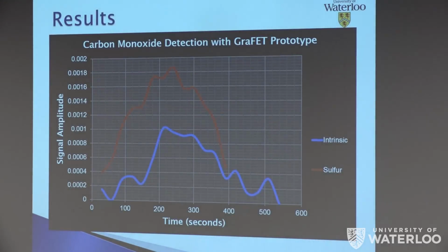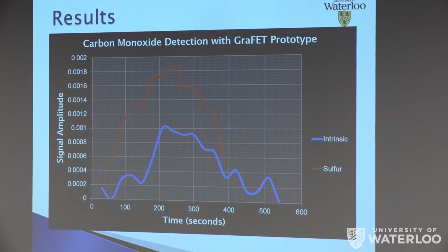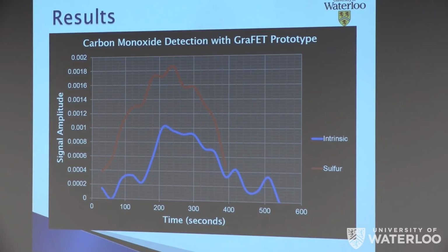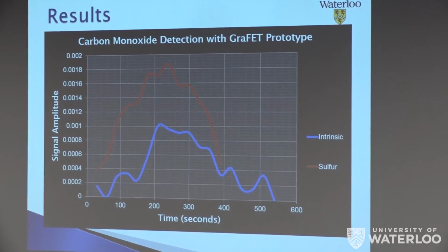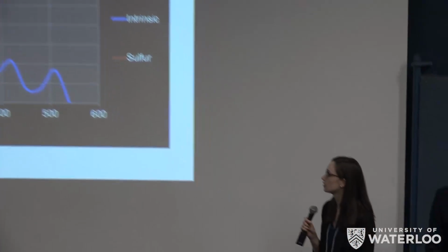So these are our exciting results for detecting carbon monoxide with our prototype. So this test was done for 100 ppm carbon monoxide, and in blue you can see the intrinsic signal, which was taken after a nitrogen baseline was established. You can also see the sulfur signal, which is 85% higher than the intrinsic signal. So this really concluded that our hypothesis was correct in that using doped graphene, you can increase the selectivity of your device.